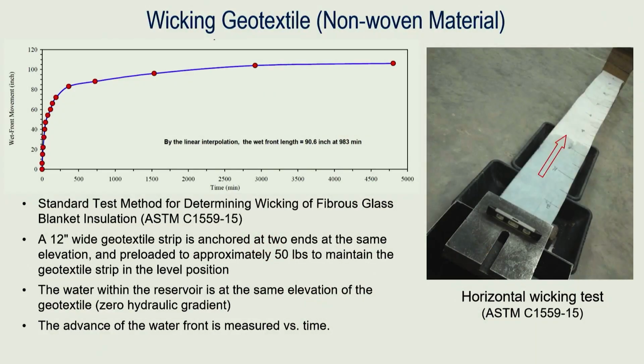And this is one of the simple tests. You have here a relationship between the suction versus time, and you can see that there is some sort of rapid increase initially as you are introducing moisture at a zero hydraulic gradient and allowing the water to move under unsaturated condition. Of course, there are another couple of tests that people use.